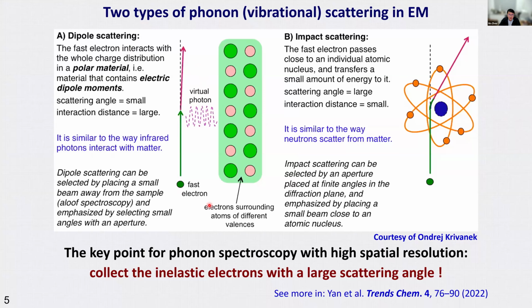it lacks spatial resolution. And the other way is that we use the electrons to hit the atoms directly, and this will excite the vibration of the material. And in this way, the incident electron will scatter to a high angle, and those high angle scatterings will give us very high spatial resolution. So this is the mode that we are going to primarily use in the following studies.